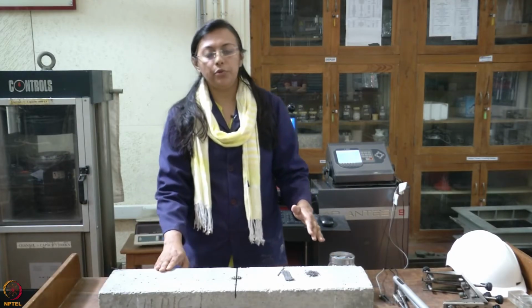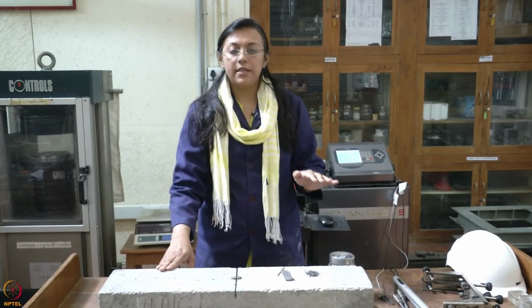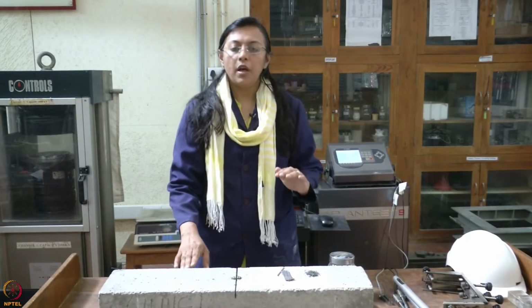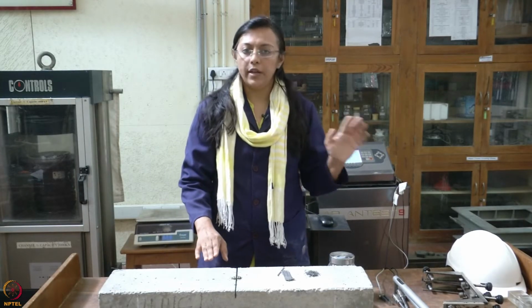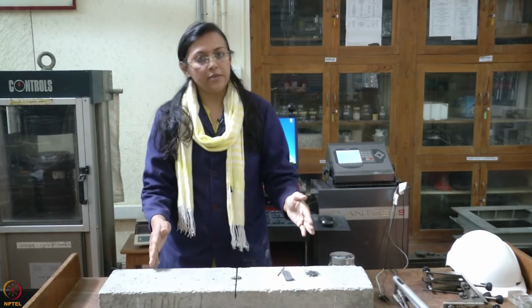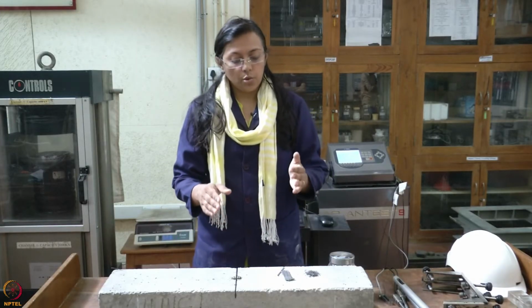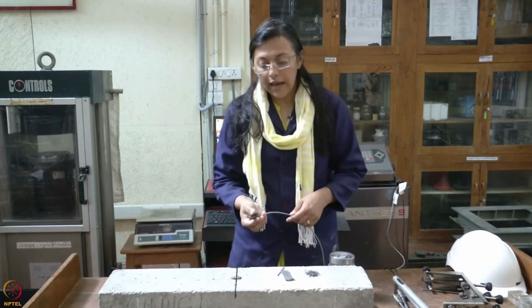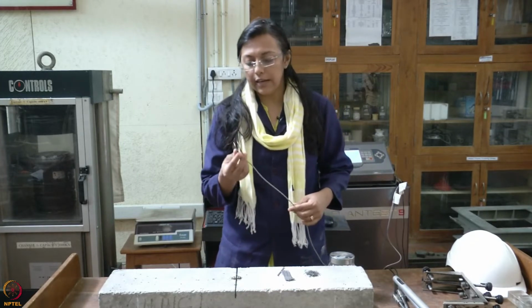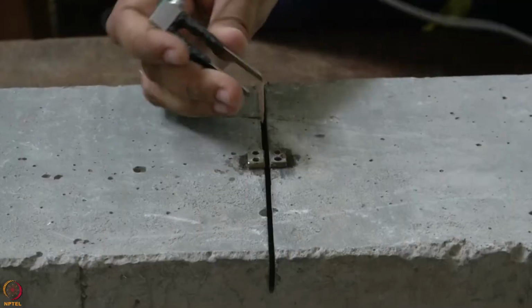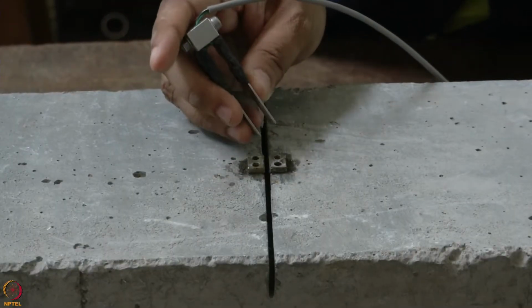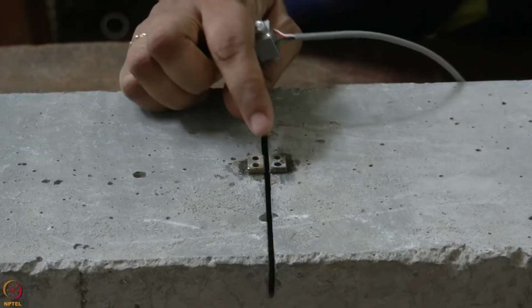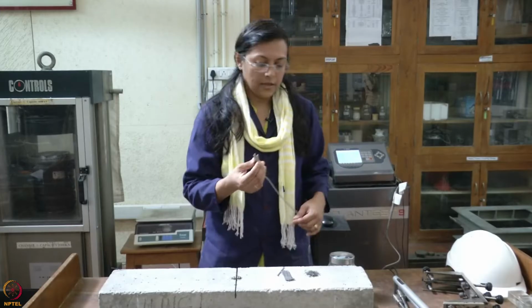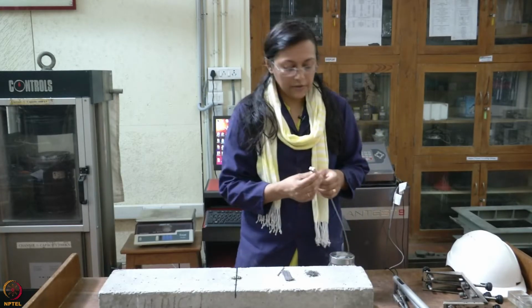As I told you before, this is a closed loop testing system, which is a displacement control test. A closed loop testing system works on a feedback control system, unlike an open loop, which is only an input and an output. This is a displacement control test in order to get the post-peak response. Here the displacement parameter is crack opening, which is controlled with a clip gauge. This is the clip gauge through which we control the test. This clip gauge is fixed onto the specimen on a knife edge, which is fixed on either side of the notch at the midspan.